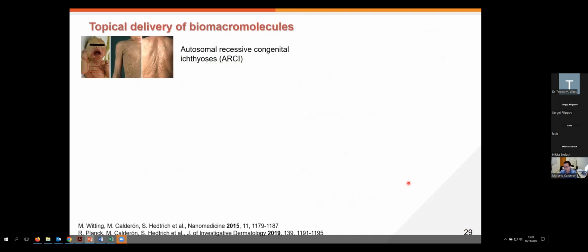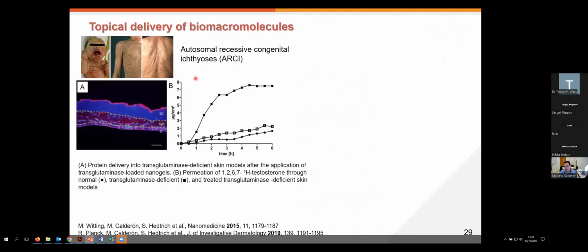And then just to show you a couple more slides on the actual application of this, for the treatment of the autosomal recessive congenital ichthyosis, delivering transglutaminase will be one of the approaches to treat this rare disease. And by this delivery of the transglutaminase, what we expect is to recover the barrier function of the skin. And this is pretty much what we could see on reconstructed skin models from Sarah as well. We could also see that whenever the disease was present, there was a high penetration of a model molecule, but whenever we deliver transglutaminase, there is no penetration anymore, and the skin recovered the barrier function.